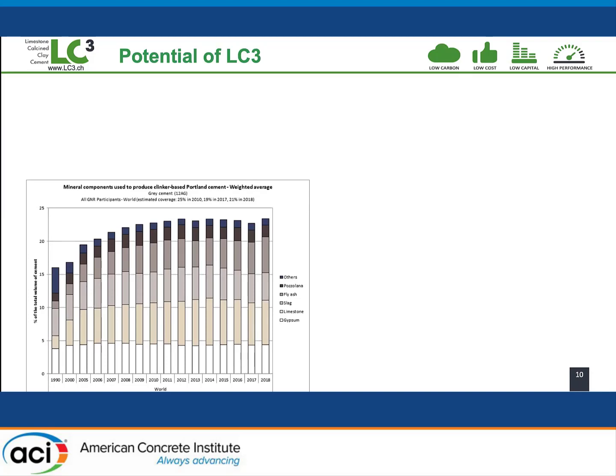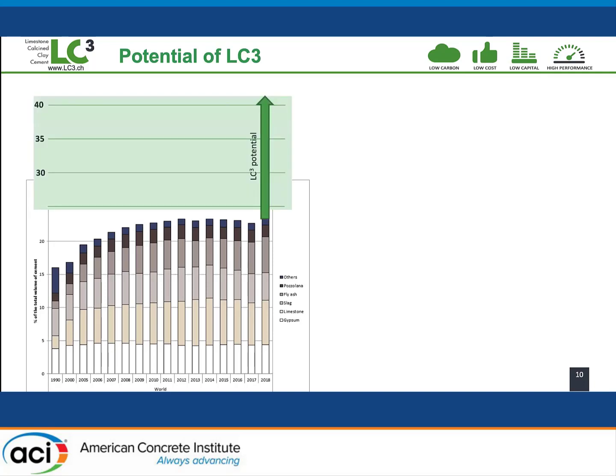But if we take this level that everybody's okay on of 60%, we see we can fill that huge extra demand for supplementary cementitious materials very easily by this combination of calcined clay and limestone, because the clays we need are very, very abundant in the world, and the most suitable materials are actually most available in those countries where the demand is going to be strongest. And making a quite simple calculation, we can see this equates to 400 million tons of CO2 per year. So that's 1% of all the CO2 we produce.